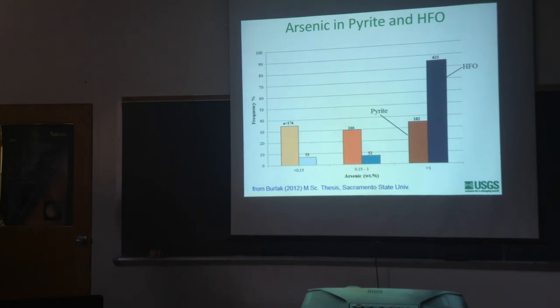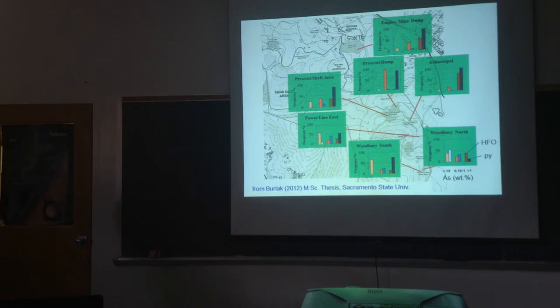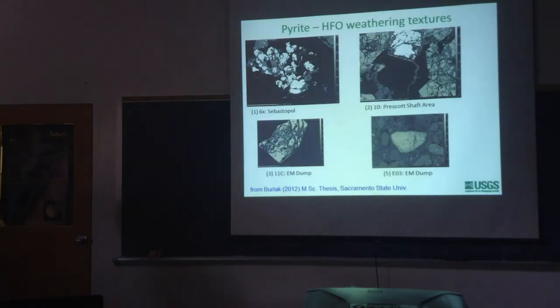And then when we look at this spatially, if you remember, as you go from left to right, it goes from low, medium to high. So at Empire Mine Dump, we see more of the high arsenic, both in the primary and the secondary. And we see this high arsenic oxides in the northern part. In the southern part, we tend to get a little more of the lower arsenic in pyrite and the lower arsenic in the weathering products as well. So there's a little bit of north-south zoning. But by and large, we see high arsenic weathering products just about everywhere.